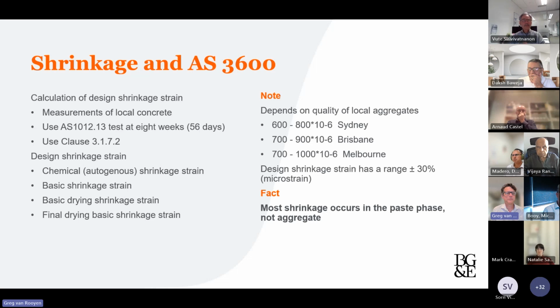It provides some numbers based on where you are in Australia and refers to the AS 1012.13 test, which is the drying shrinkage test. And the standard does try and account for early age autogenous shrinkage, some basic shrinkage strain, and volume reduction. There's a fair range around Australia. The codes talk about some typical values, but in certain parts of Australia, shrinkage can vary quite widely from different aggregates. And the standard talks about a plus or minus 30% range.